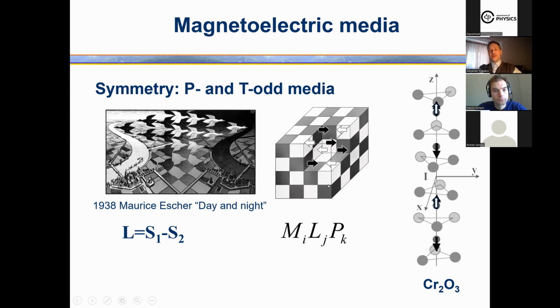So physically, that means that ions are transformed from one sublattice to another with magnetization reversal. It's very good for analysis of antiferromagnets, since there are at least two sublattices, and they are, as a rule, related by some symmetry elements.